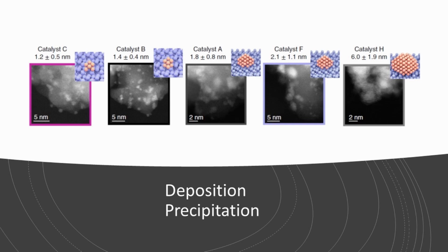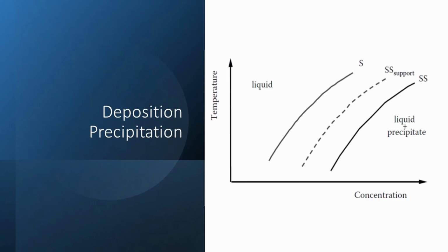The method of deposition precipitation is a modification of the precipitation methods in solution. It consists of the conversion of a highly soluble metal precursor onto a support and not in solution. The conversion into the precipitate can usually be achieved by raising the pH of the solution. And to perform the precipitation exclusively on the surface of our support, two conditions must be fulfilled.